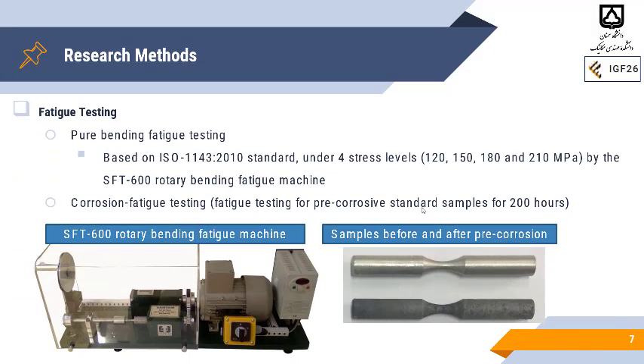For fatigue testing, we have used pure bending fatigue testing based on ISO 1143. That is our standard. That is the standard that we have used under 4 stress levels: 120, 150, 180 and 210 megapascal by the SFT 600 rotary bending fatigue testing machine.